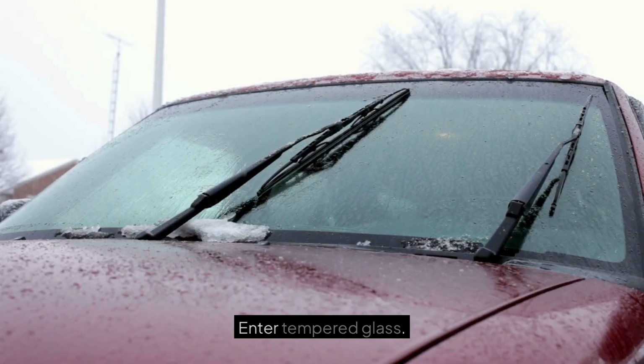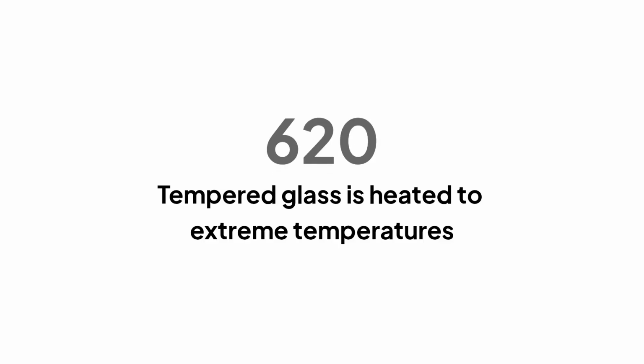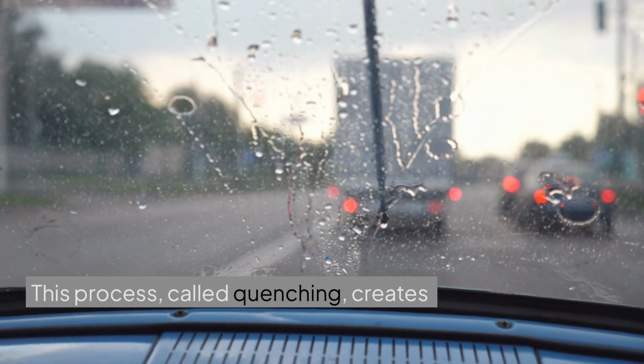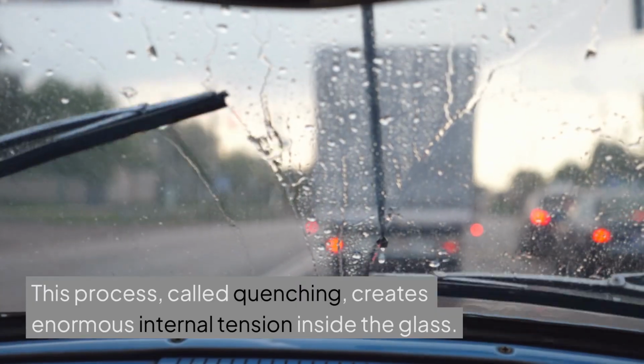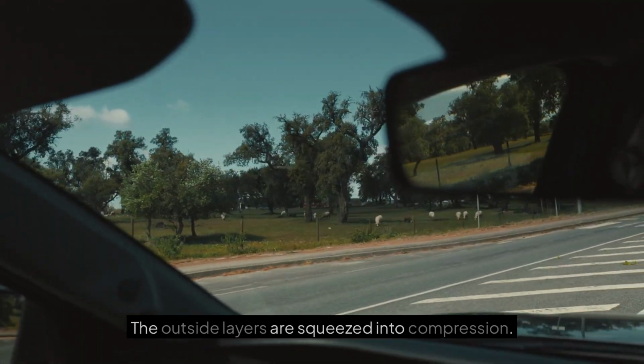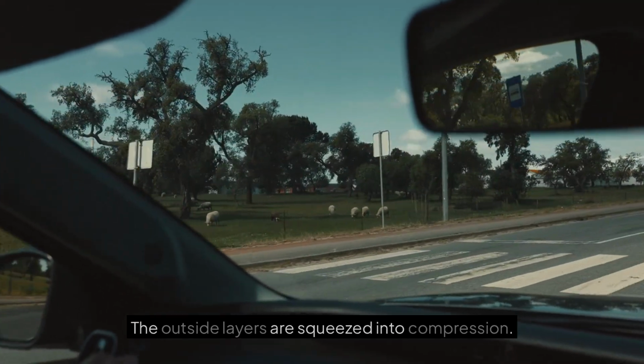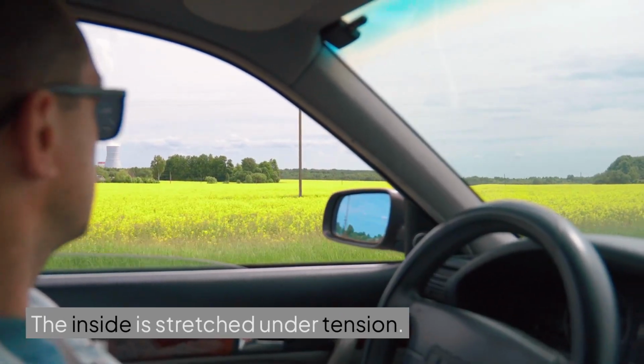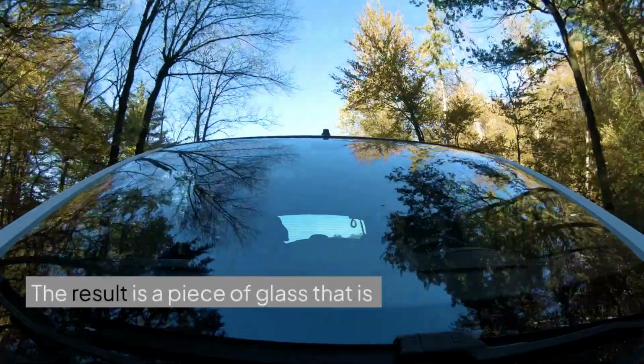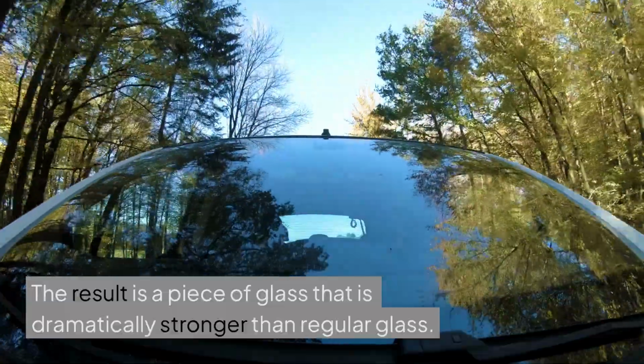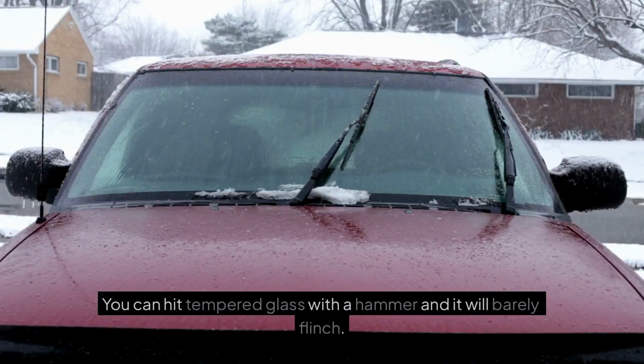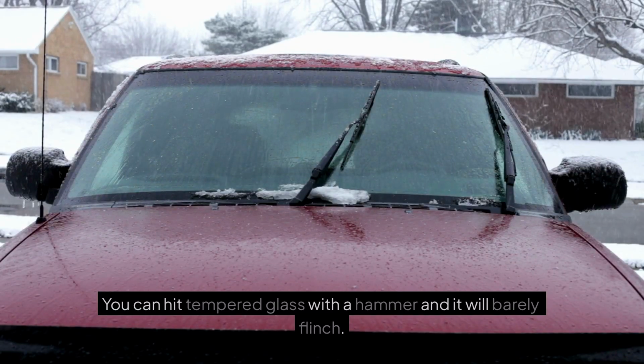Enter tempered glass. Tempered glass is ordinary glass that has been heated to an extreme temperature, somewhere around 620 degrees Celsius, and then rapidly blasted with cold air. This process, called quenching, creates enormous internal tension inside the glass. The outside layers are squeezed into compression. The inside is stretched under tension. The result is a piece of glass that is dramatically stronger than regular glass. You can hit tempered glass with a hammer and it will barely flinch.